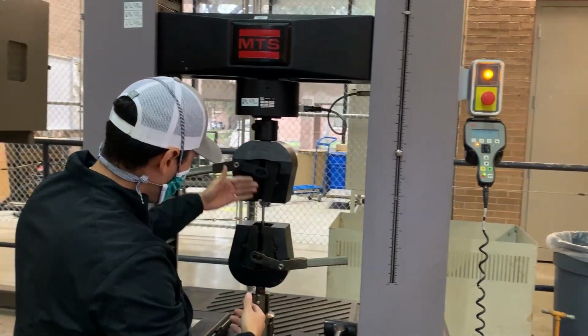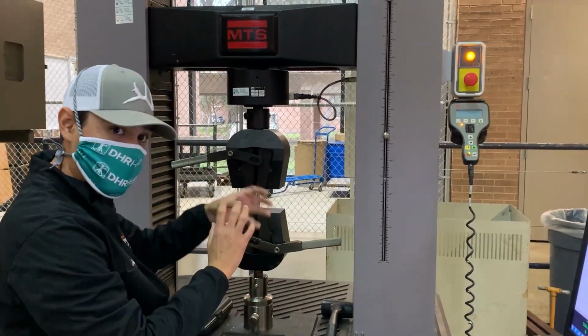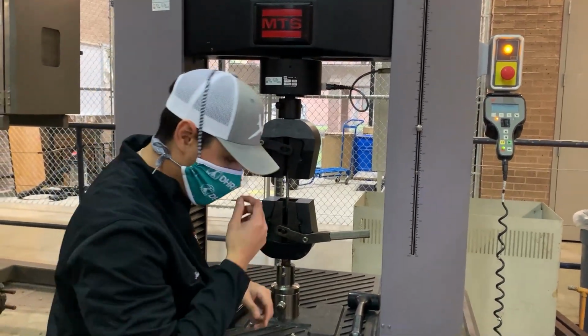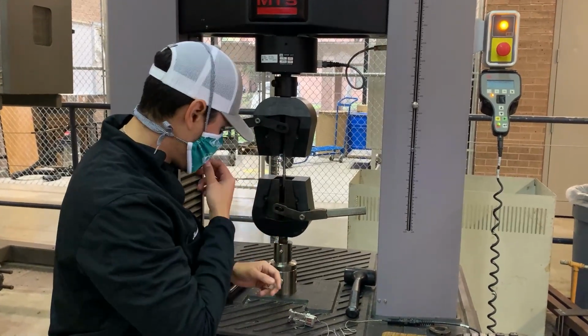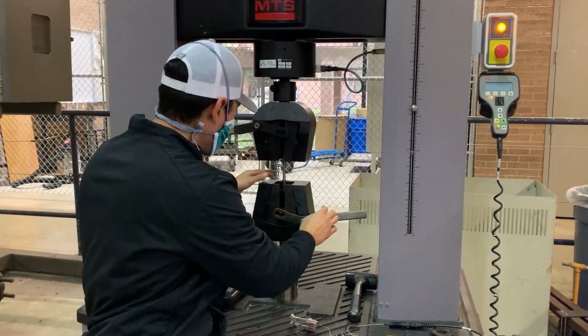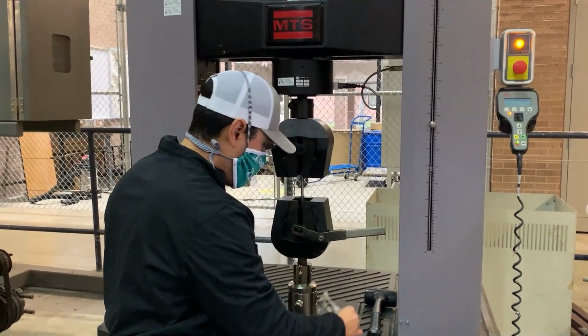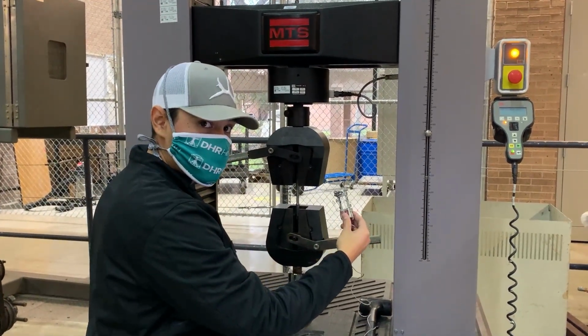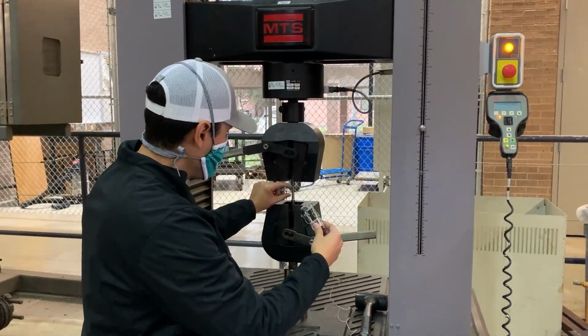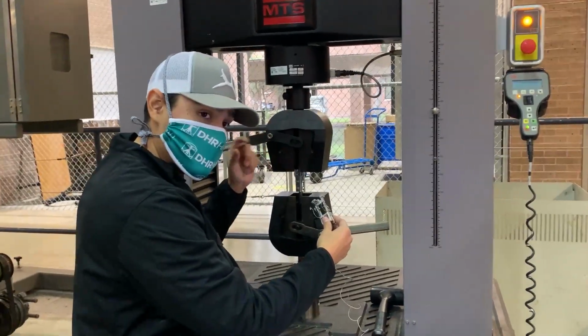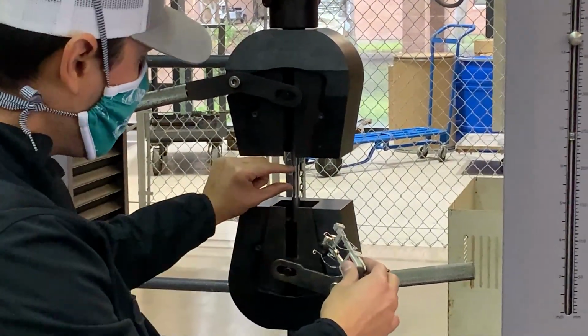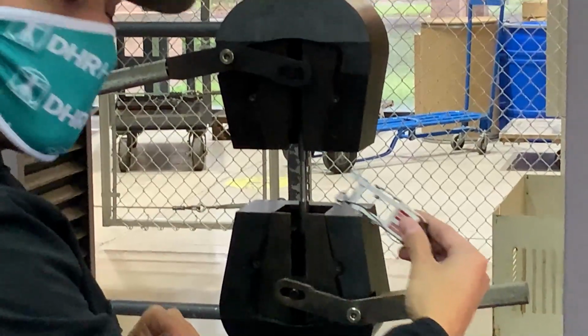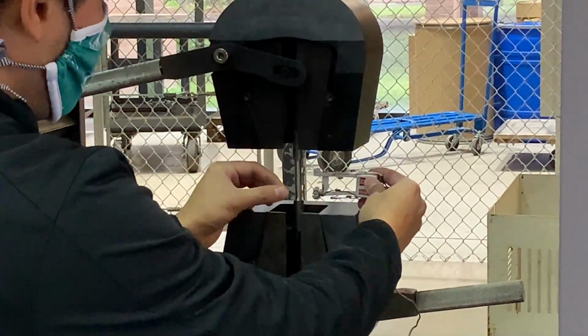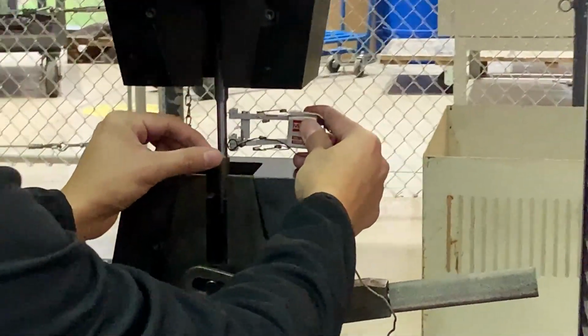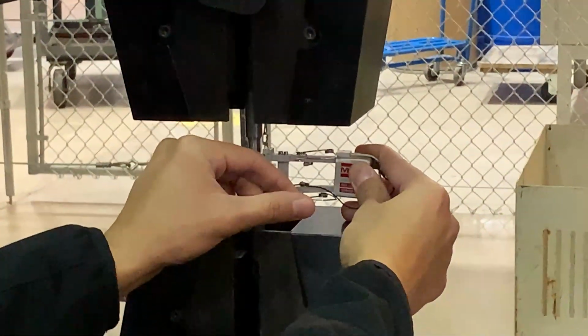You want to make sure that the faces are flush. If they're rotated, you'll add some torsion to it, some torque, which will affect the results. So once we have our sample in place and secured, we're going to place our extensometer, and this will measure the minute changes that we can't see visually. So the change in length that's going to happen, using our extensometer, this gauge will be applied to a location where we think it will fail.